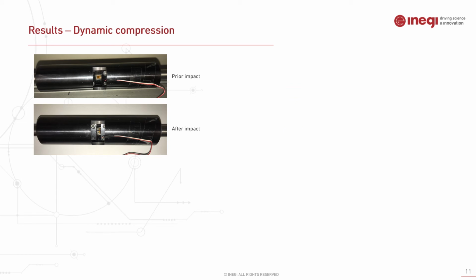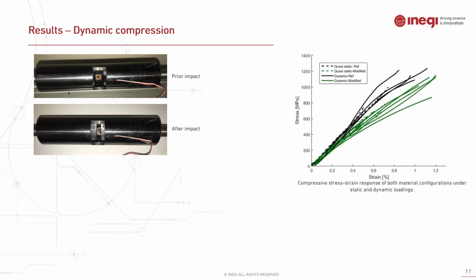You can see the test coupon before and after being subjected to the compressive loading at a velocity of 6.5 meters per second. And over here, we have the dynamic compressive behavior of the samples, and as you can see, they're quite rate sensitive, demonstrating an increase in the ultimate strength and failure strain values. At high loading rate, the compressive strength increases by 62% for modified and roughly 93% for reference materials. But despite that, loading rate was found to not influence the elastic modulus of the material. And again, similar to the static results, modification of these materials appears to reduce the elastic modulus.